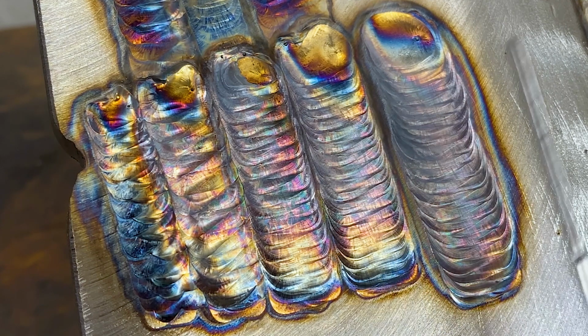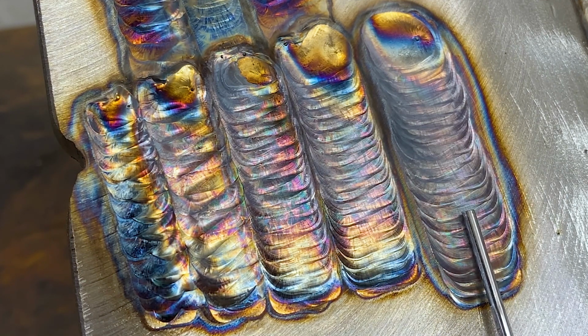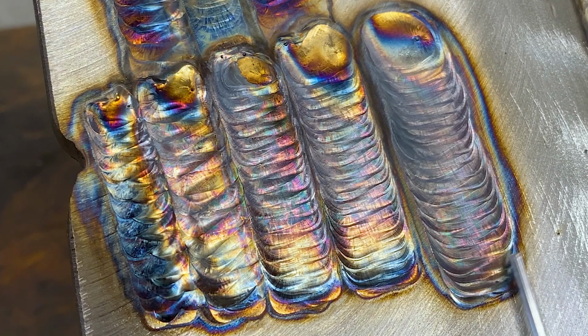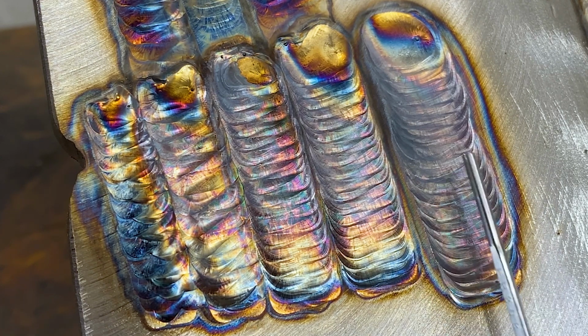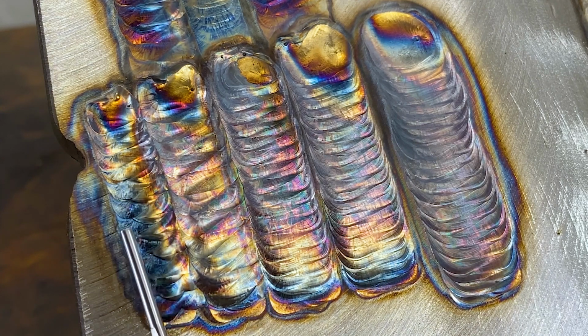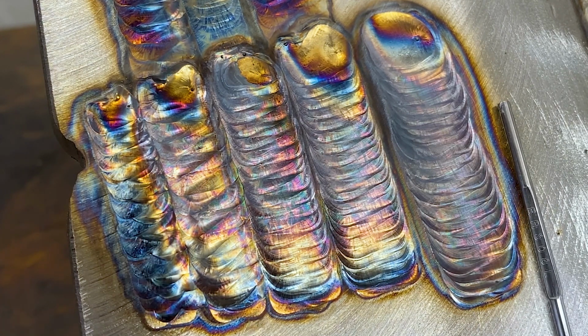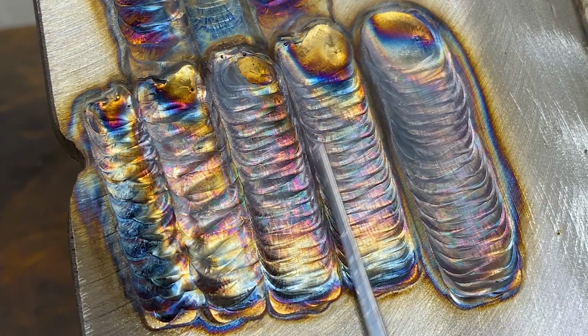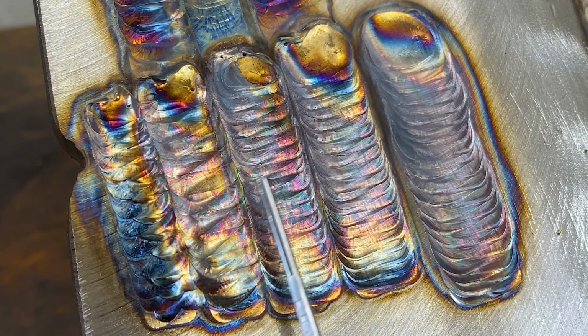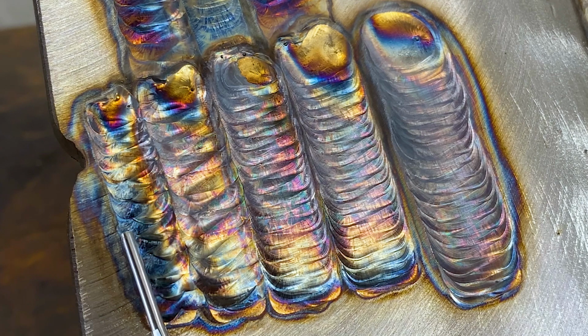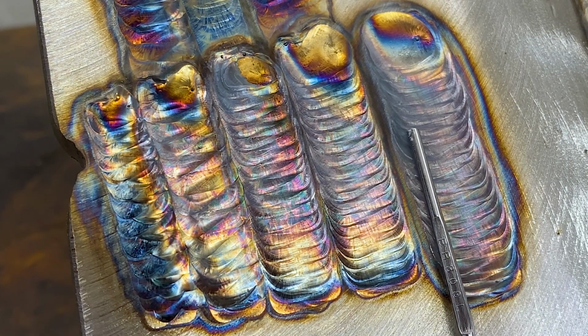Moving forward, I stepped it up to 200 amps, and you can tell right away, especially when you're watching the arc footage, the puddle is uncontrollable. The heat affected zone is insane. The oxidation rate, it's gray. It's no bueno whatsoever. So I just wanted to show from the bottom of the spectrum to the top and kind of give you a step-by-step in increase to see what a difference 90 amps is versus 200.